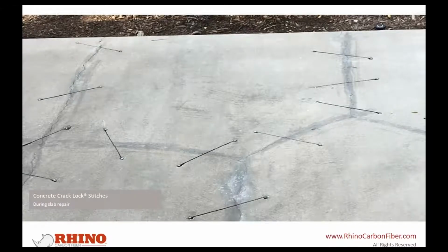Here's another example of crack locks on a slab. You can see here, kind of unique about this is this engineer called for the crack locks to be installed on kind of an angle rather than being directly perpendicular. The reason for that is they were worried if they put them all in line, due to the age of the slab and condition of the slab, that they would create a possibility for fractures to occur outside of the crack where the holes were drilled. So this contractor was advised to offset them and put them on different angles to avoid that from happening.